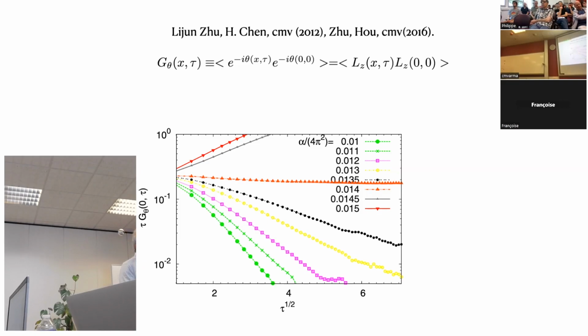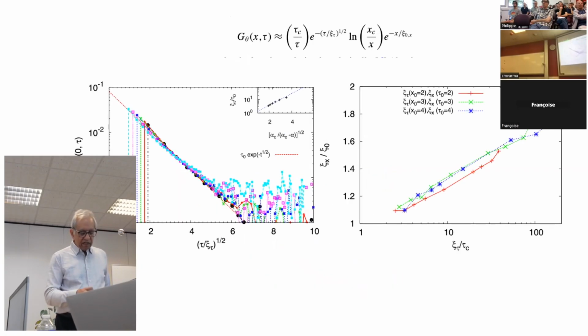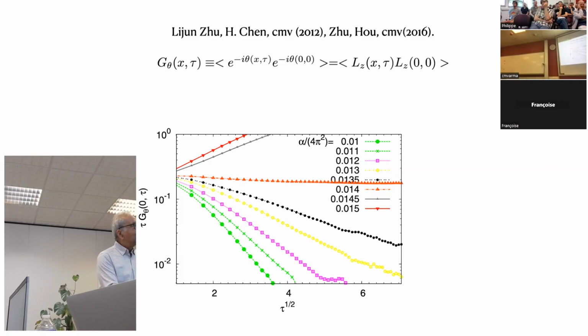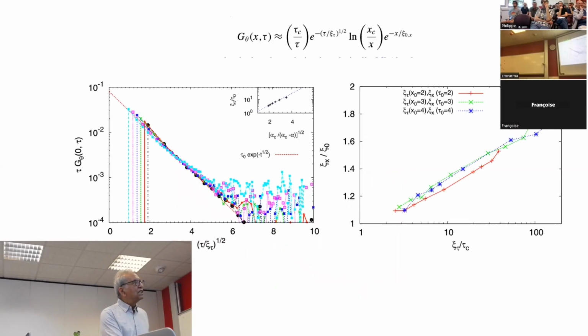And in fact, in our paper, I had this wonderful guy. He's compulsive. He added 2 more decimal places in here, and so we have a dense set of things here, but they only clutter up the thing. And then you find that all of these curves, up to the place where they get noisy, collapse onto a single thing where you can define a correlation length in time as a function of these parameters, and well, it's a limited region, but this thing is going exponentially as e to the minus t over tau.